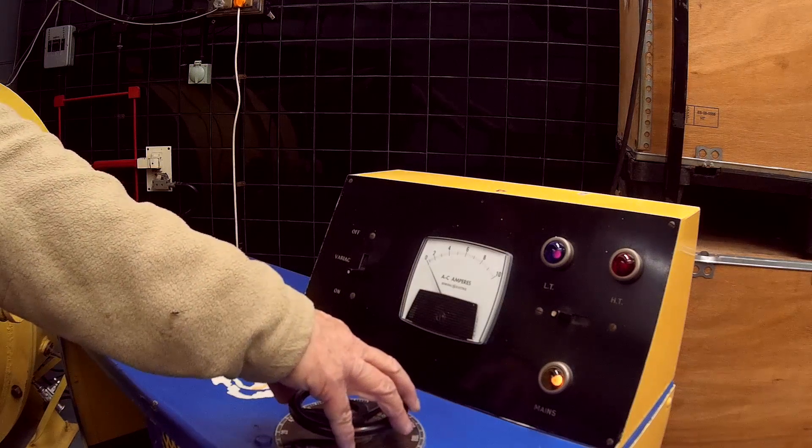Okay, so I have high gas, and those coils as they warm up, you can see the current change. Now you can see that they're changing, and as the aluminum melts on, you can see the current go up. Yes, there's the one firing, yes there's the other one firing. And then as the aluminum melts off, you can see the current return again. The aluminum adds to the conductivity of the tungsten.